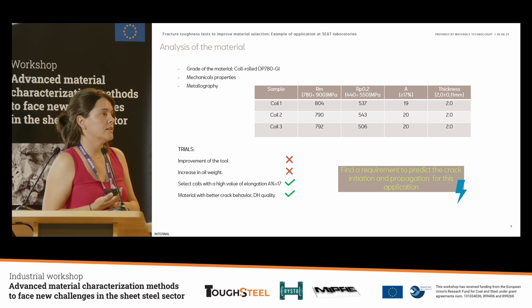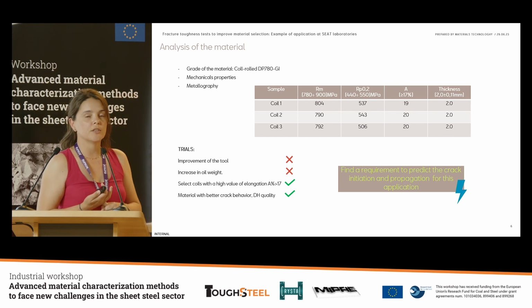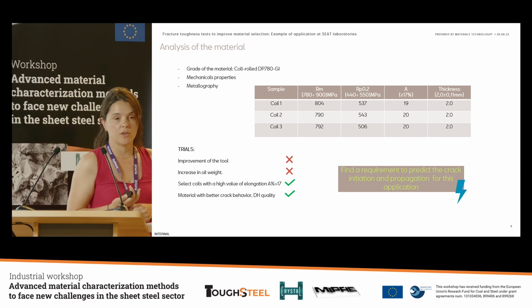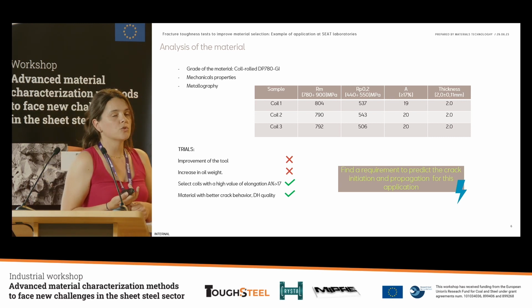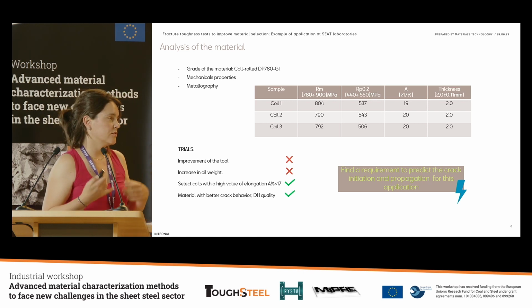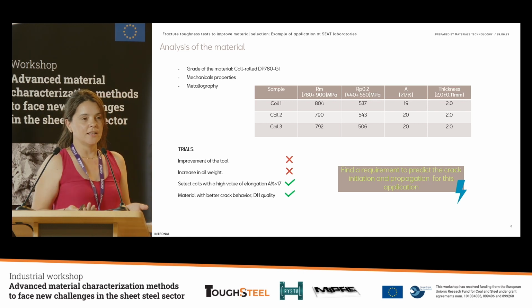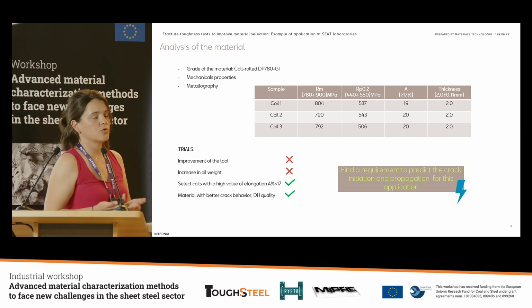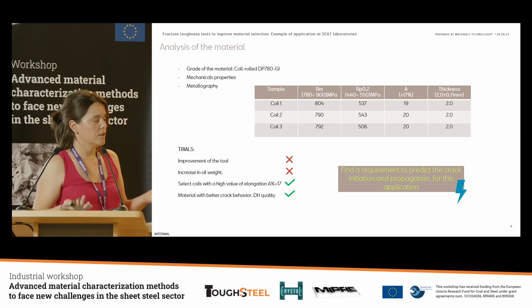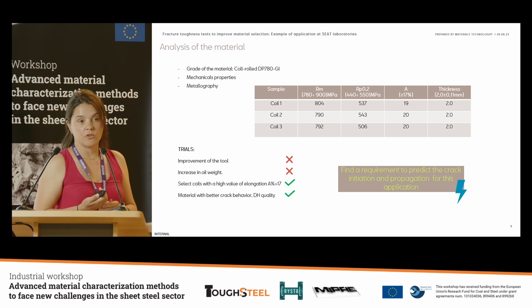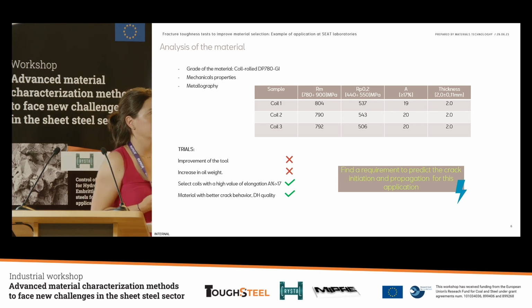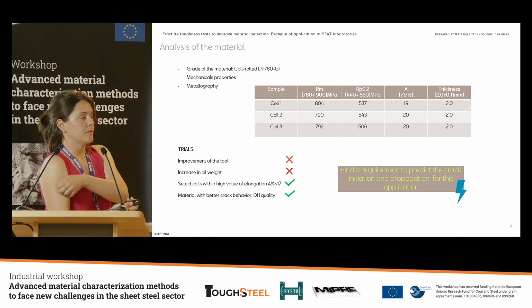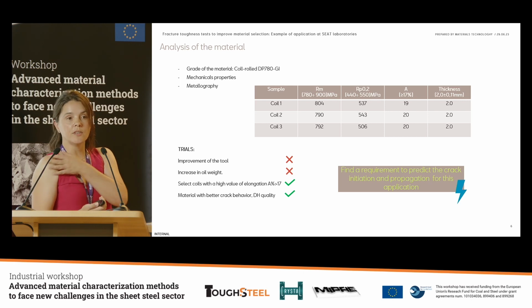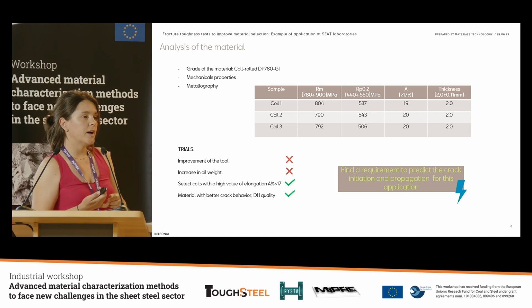Okay, we found that the coils with more than 17% of elongation, the behavior was really good. But it was not possible for the supplier to give us always this elongation because it was not a robust measure, so we decided not to implement. It was not possible. And then we changed for another quality of material, the DH quality of material.